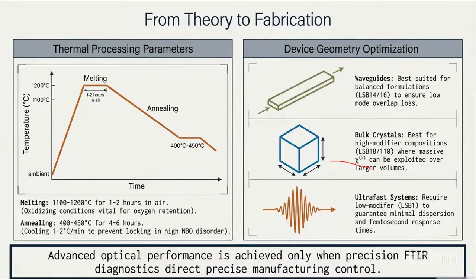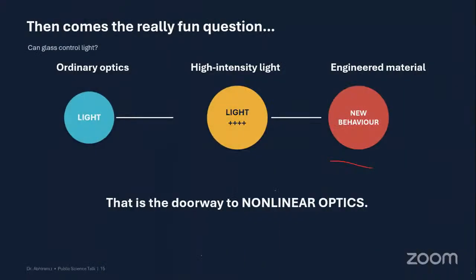I can definitely draw a waveguide of beta barium borate inside the glass matrix, which is completely encapsulated. That beta barium borate, which is hygroscopic, has been encapsulated with a barium borate environment, which is completely stable, and thereby the hygroscopic challenges are reduced. So this is one of the major challenges that is open to all of us. As students of glass science, we can work on this line.